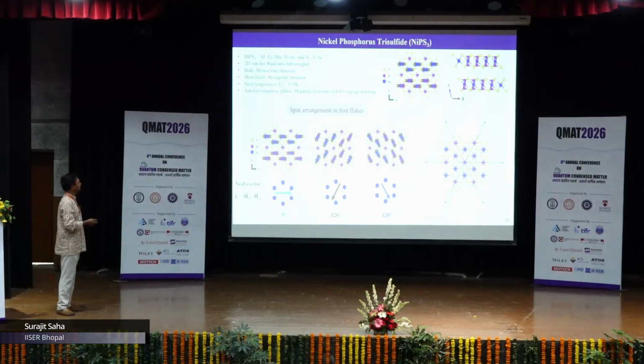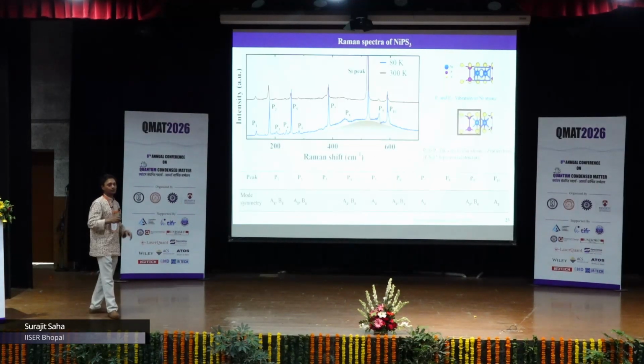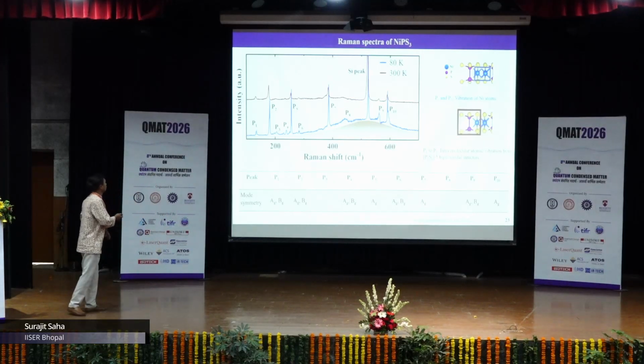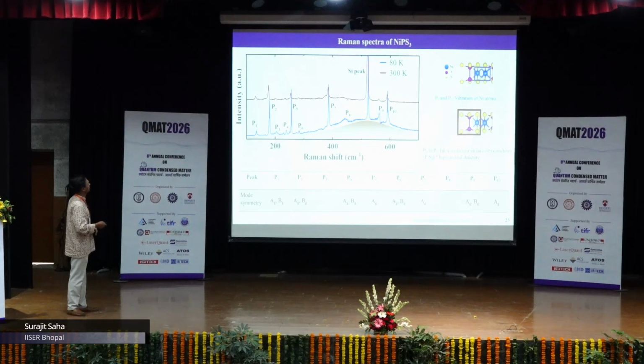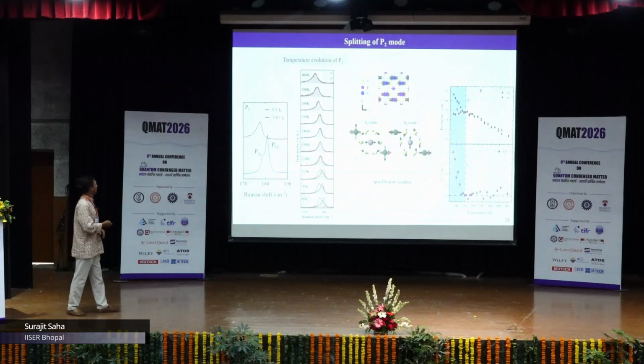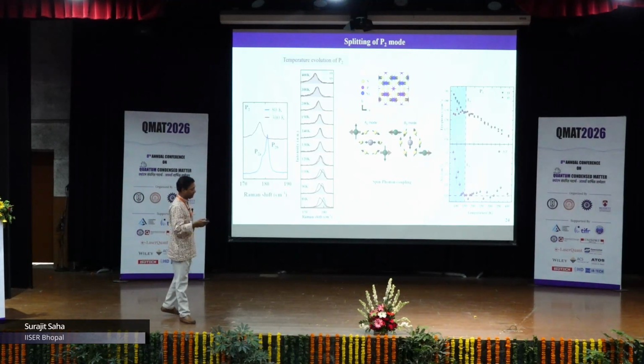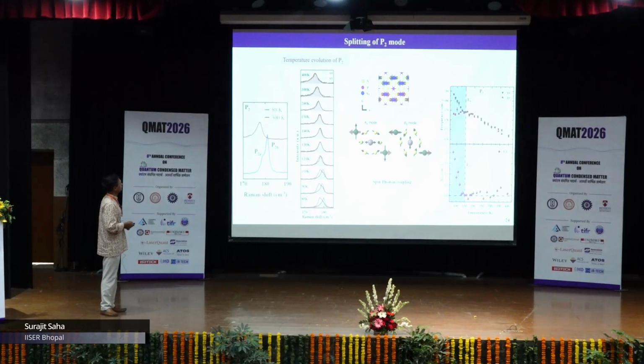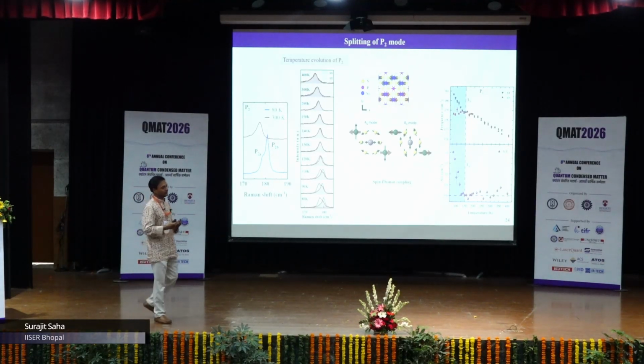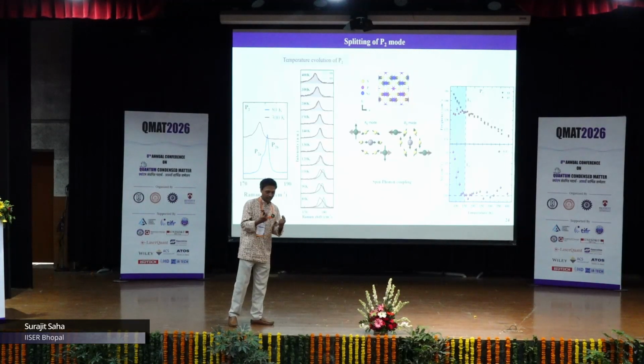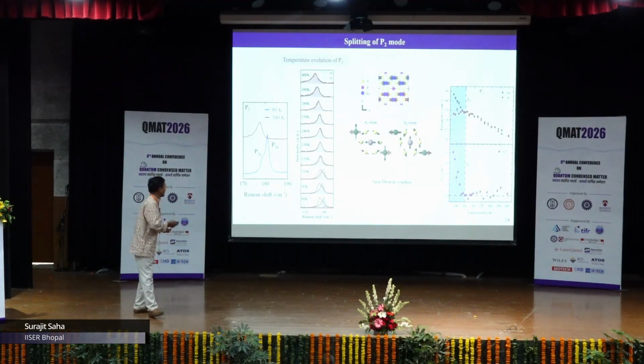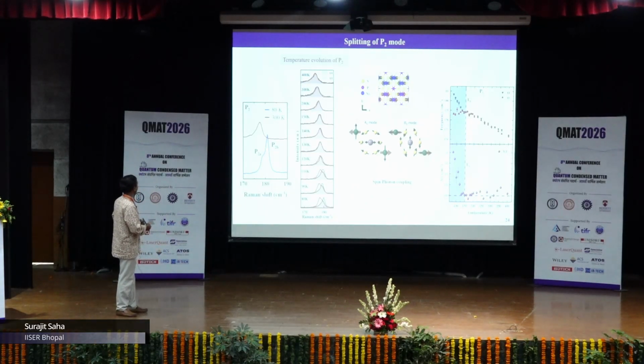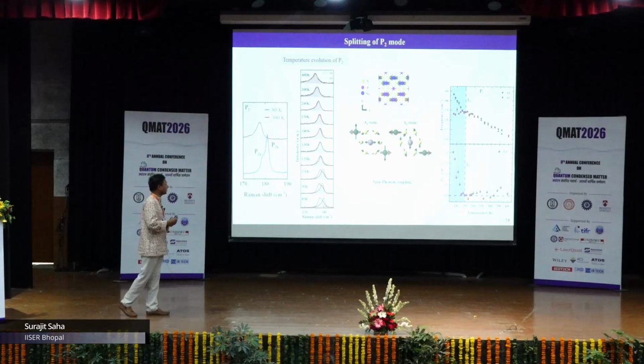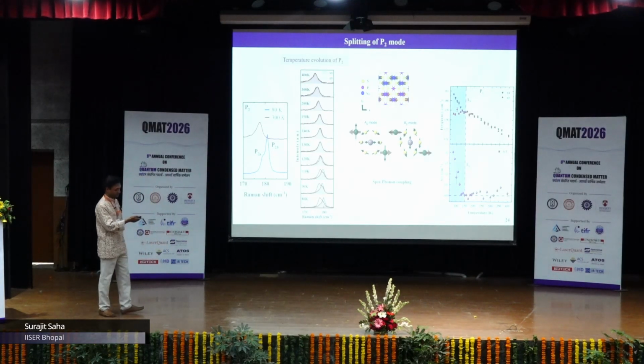We looked at this using Raman, and in Raman we could map these 3 different orientations of the spin. Here is the Raman signature in the antiferromagnetic structure, where you have the 2 magnon mode along with various other modes. The most important feature here is the spin phonon coupling. This spin phonon coupling has an anisotropy depending on whether the vibration of the mode, the atoms, is along the direction of the spin or normal to the direction of the spins. That gives an anisotropy in the spin-phonon coupling, and based on that, this particular mode will show a splitting, and that splitting becomes our signature to understand this magnetic ordering as well as the spin orientations.